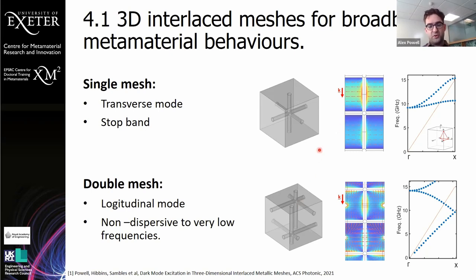So you might think that if you take a second mesh and put it in the middle, you get more of the same, just with properties changing due to the increased density of metal. But actually, you get something completely different. At low frequencies, you see this longitudinal mode. We've made grids of about a centimeter by a centimeter, and from about 10 gigahertz down to nothing, it's essentially non-dispersive, which is extremely rare for metamaterials, which tend to work around the resonances of their meta-atoms, so they have the properties you want in a narrow range of frequencies. But these materials are incredibly broadband, which is exciting. And the mode they create is actually longitudinal, so the polarization is in the same direction as the wave vector, the direction of travel through the material, which is also really interesting.